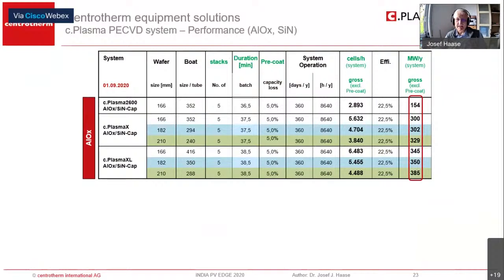Here you see just what this means in megawatt when I take our standard processes of the machines. On top, the small one, which had about 150 megawatts in Alox, and the Plasma X about 300 megawatts. And this is quite independent of the wafer size, as the area of the graphite plates in the graphite board are quite similar for the different wafer sizes. And if you go to the Plasma XL, the next extension, then we run about 350 megawatts. Next.